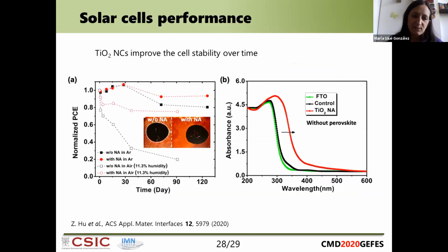But the result that was very interesting here was that, as I told you, one of the most important problems of this kind of solar cells is the stability. And of course, we measured the stability. We measured the performance of the system through 3 months, measuring the values of the efficiency every 15 days, every 30 days. The ones with nanocolumns were quite stable. Well, they degrade a little bit, but not much, while the ones without nanocolumns were degrading much more. So one of the most interesting results here was that adding the nanocolumns favored a more stable cell with time.